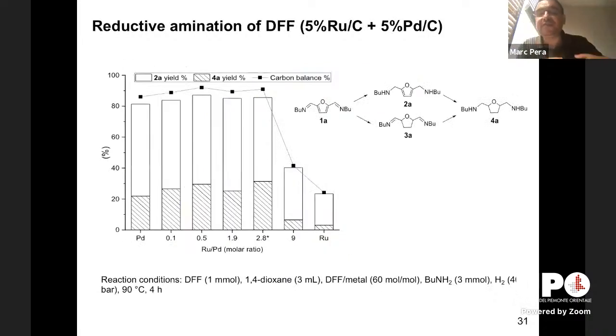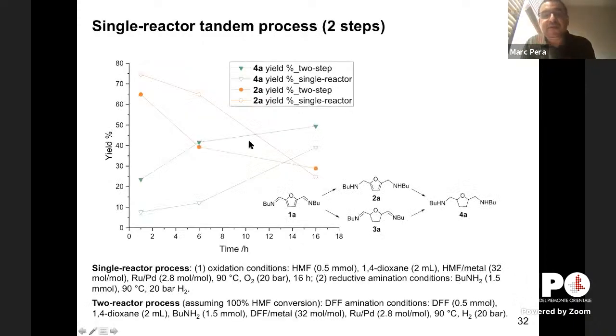The same happens for the second step. So the system that is operating is the palladium carbon, the ruthenium is not active for this reaction. So just by optimizing the ratio, in our case 2.8, we can have excellent results only for the second step in the presence of the two catalysts together. So here you have the example of the single reactor process compared to the two-step process.